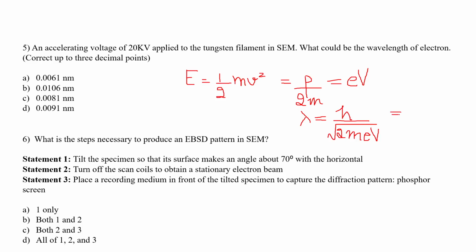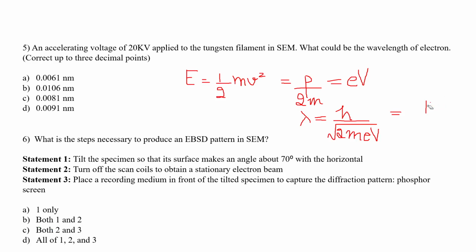If you do all these calculations, on an average you will have lambda equal to 150 divided by voltage whole to the power 1 by 2.